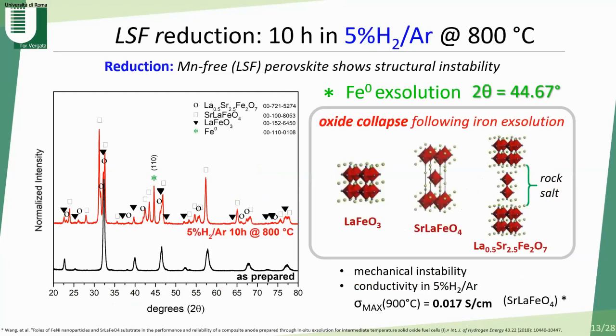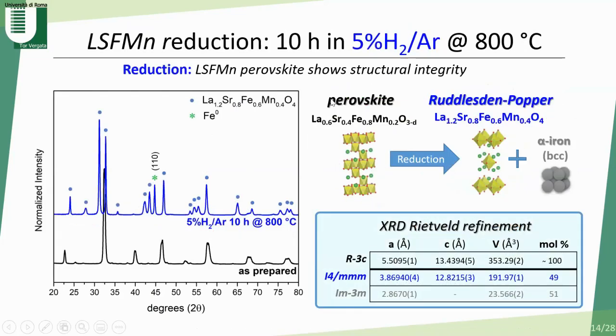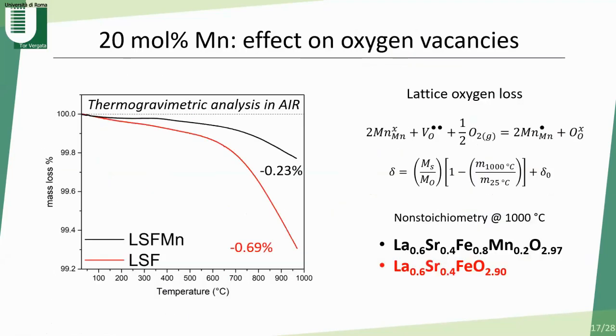I want to show you what happens during reduction of the manganese-free LSF perovskite, a complete structure instability. As you can see from this XRD, we can observe the iron exsolution in the pattern, but also the decomposition and the oxide collapse, reducing in hydrogen at 800 degrees C. The same reduction treatment in the manganese-substituted LSF perovskite oxide shows good structural integrity, because there is a transformation from the single rhombohedral perovskite of the as-prepared compound into a Ruddlesden-Popper structure with exsolved iron, which is the role of manganese doping.